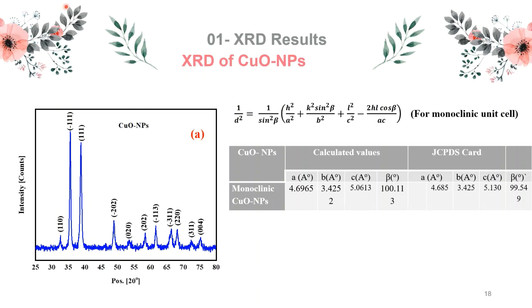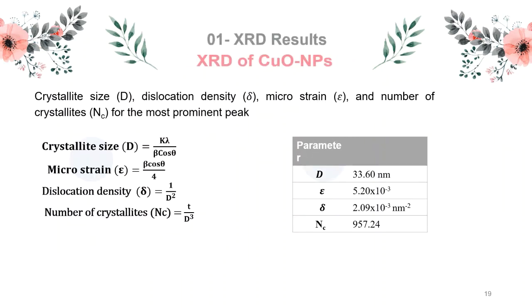nanoparticles synthesized. Using this equation for the monoclinic unit cell, we calculated the lattice parameters of the prepared copper oxide nanoparticles, which are in good agreement with those of the card. This table presents the calculated crystallite size, dislocation density, microstrain, and the number of crystallites for the most prominent peak of copper oxide nanoparticles, which was calculated using the following equations.